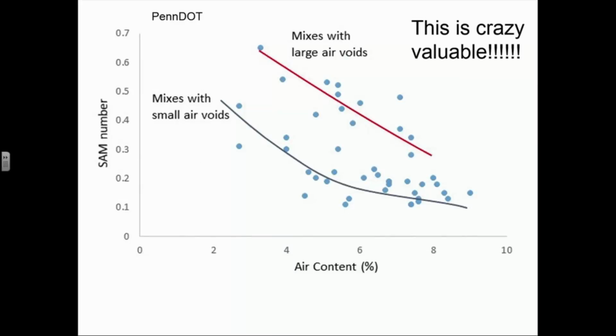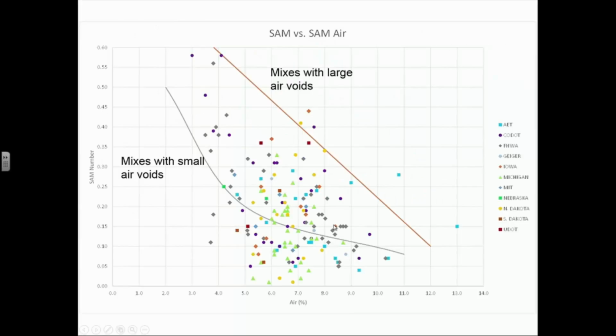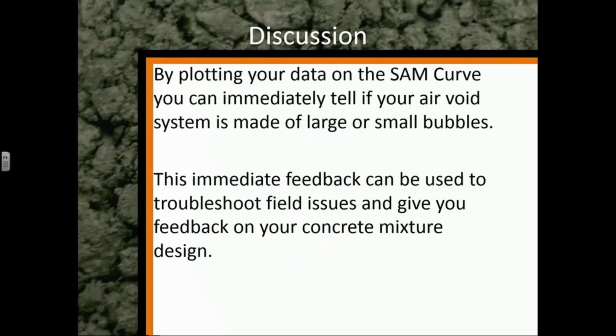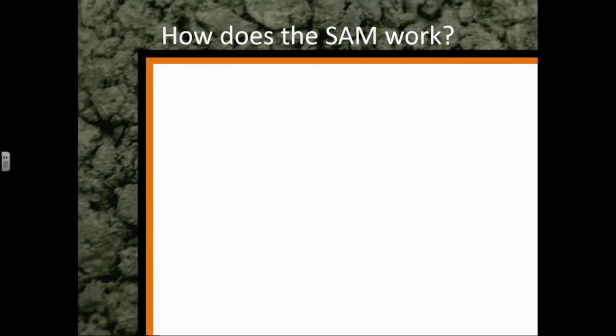So here's some data from Pennsylvania DOT. And look at this. Think how valuable this is. They knew all these mixtures immediately would have large air voids. They knew all these mixtures had small air voids and these were somewhere in the middle. This is crazy valuable. These are all data sets from 10 or 11 different state DOTs. And again, they could find out immediately if they had small air voids or possibly really small air voids, or they were having coarse air voids or possibly really large air voids. Again, that immediate feedback is really, really helpful and important. So by plotting your data on the SAM curve, you can immediately tell if your air void system is made up of large or small bubbles. And this immediate feedback can be used to troubleshoot field issues and give you feedback on your concrete mixture design almost instantly. So how does this super air meter work?